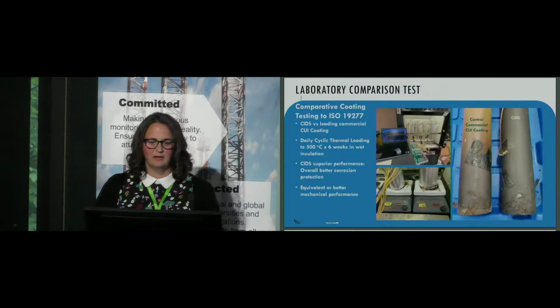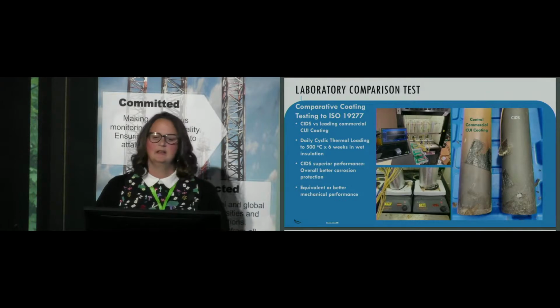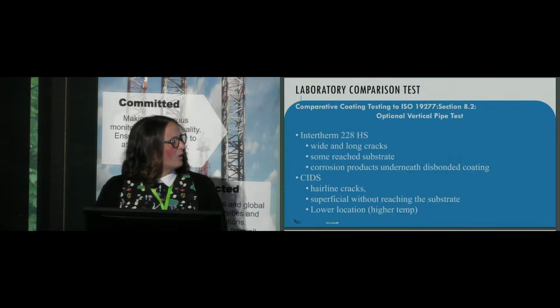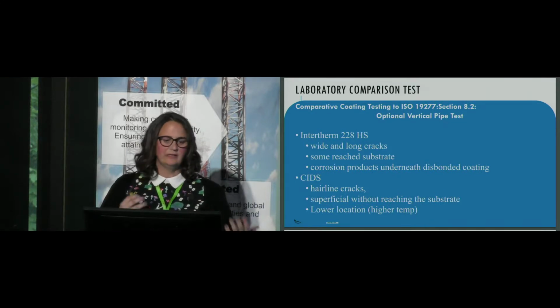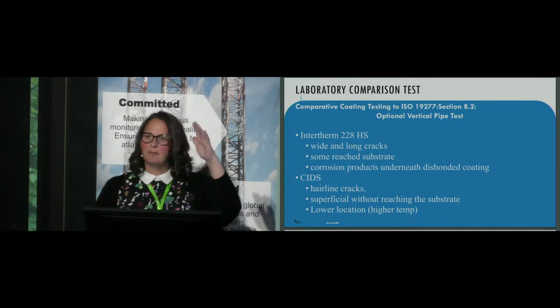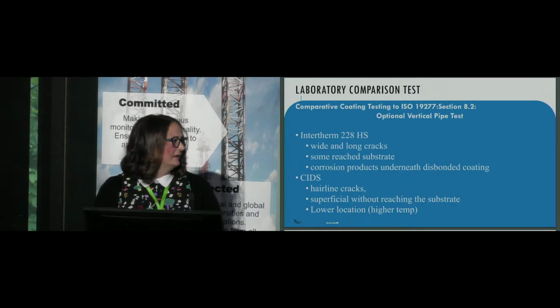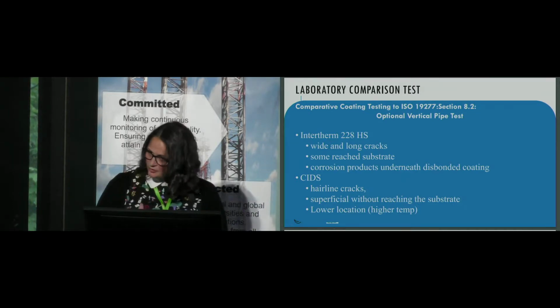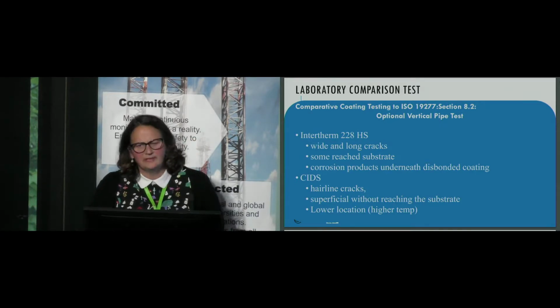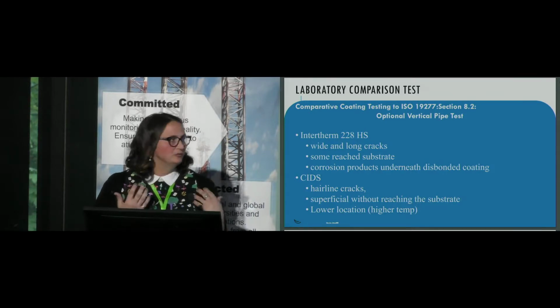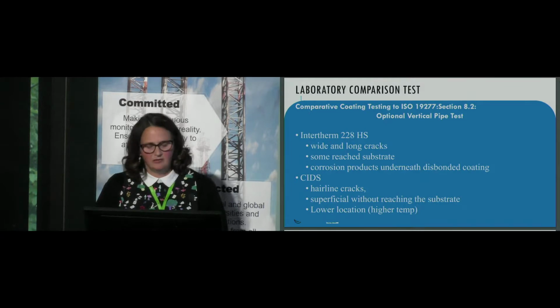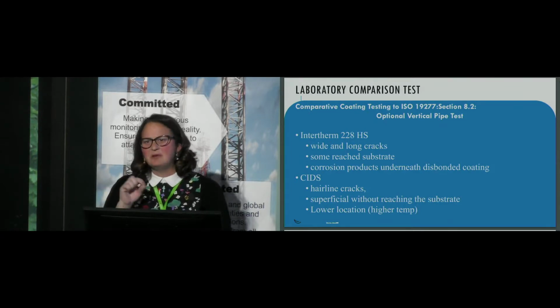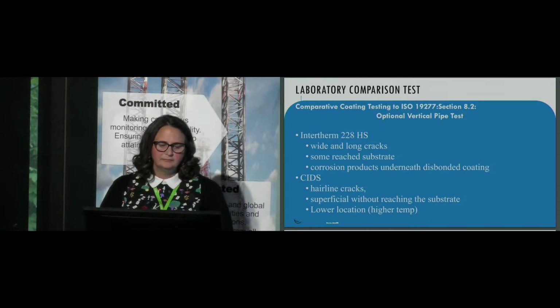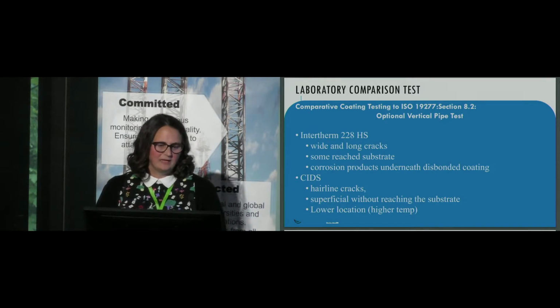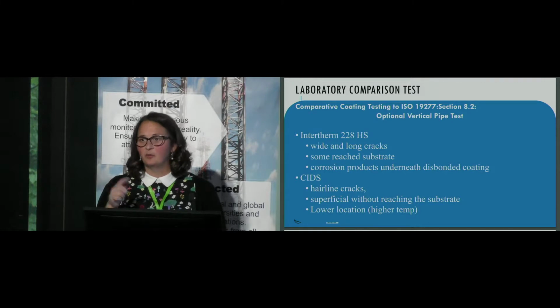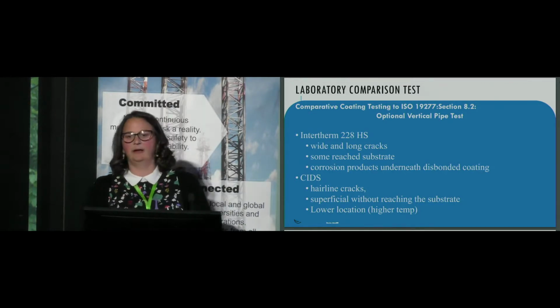We had all of these hot plates that go up to 500 C, so there's a whole lot of damage right at the bottom. But what we found is that while both of them did eventually crack, the Intertherm was cracking much higher up, at a lower temperature. The CIDS had some cracking closer to the bottom, and that's the super high temperature that you would never really be running most pipes at. Also, the Intertherm that we used had really significant cracking. The CIDS had hairline cracks, maybe more in number, but they never reached the substrate, so there was no corrosion. But with the Intertherm, some reached the substrate, and there were corrosion products found under it.